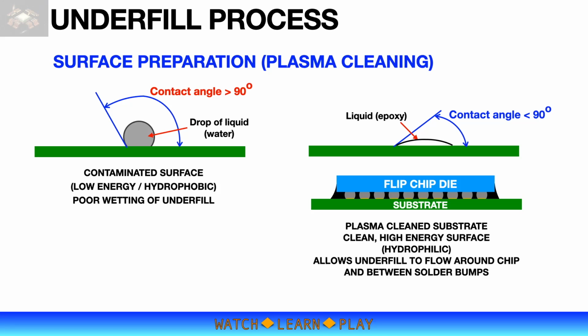Plasma cleaning uses gas such as oxygen and argon to remove organic contaminants. With the right gas mixture, it will remove organic contaminants and does not leave residue. It is also a green process, wherein gases used are non-toxic and have a harmless waste. After plasma cleaning process, the substrate surface has high energy and becomes hydrophilic, allowing underfill epoxy to flow properly around and between solder bumps.